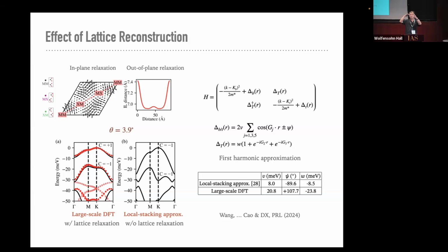If you think about the band dispersion, in graphene you draw a curve, say that's the K point, right? But in TMD, you keep going to the gamma point, the bands come back, and you have a sort of secondary pocket at the gamma point. They are very close in energy to the K point. Now, if you fold them back, you're going to have two sets of Moiré mini bands, one from K, one from gamma. So those are the gamma bands.